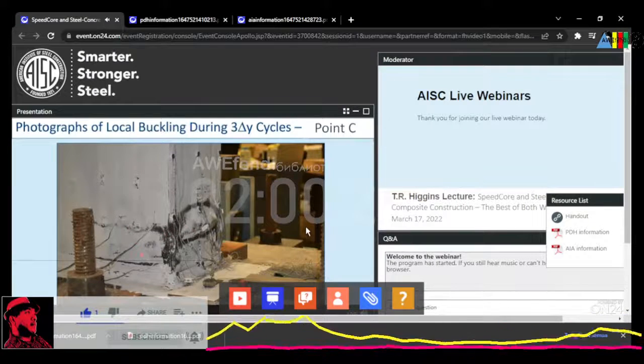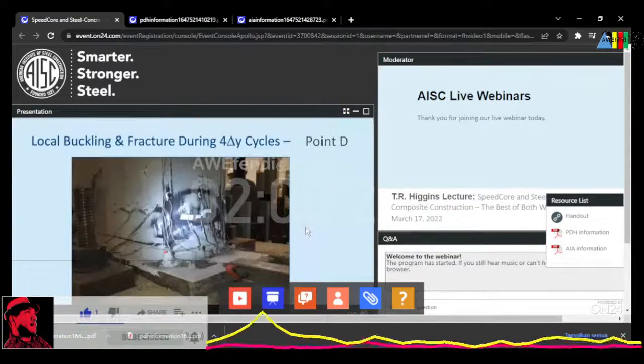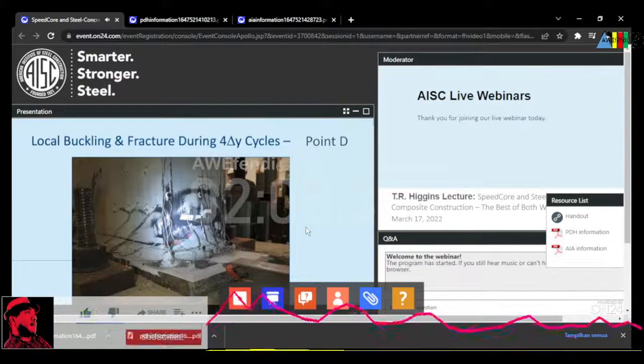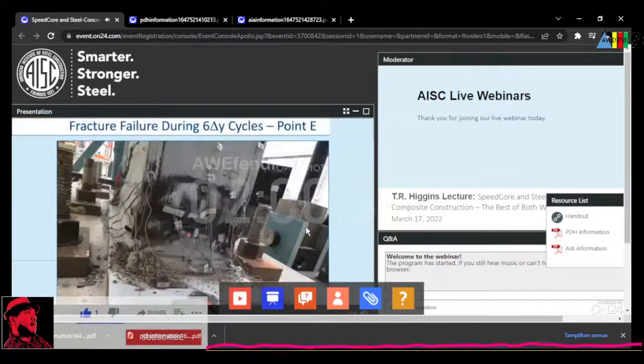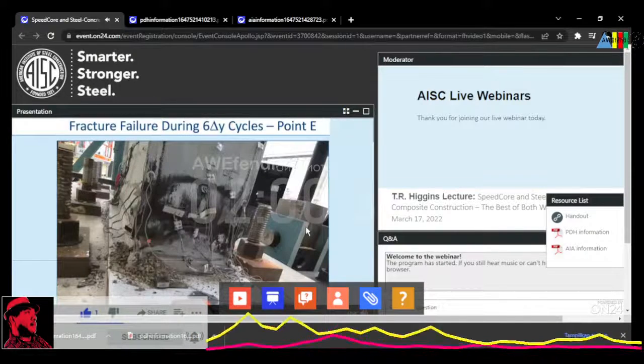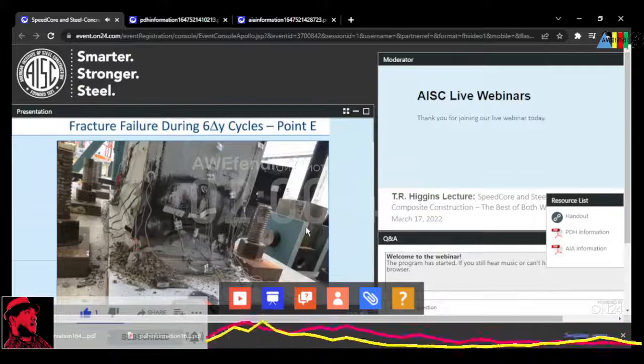Extensive local buckling occurred during the 3 delta Y cycles, which was point C, corresponding to the occurrence of web local buckling as well. Extensive local buckling and fracture, point D, is shown here during the 4 delta Y cycles. Complete fracture, point E, and concrete debris oozing out during the 6 delta Y cycles are shown here.